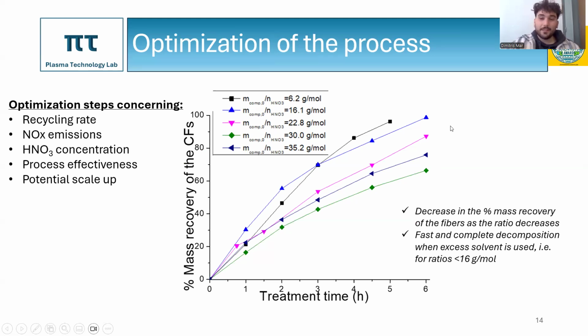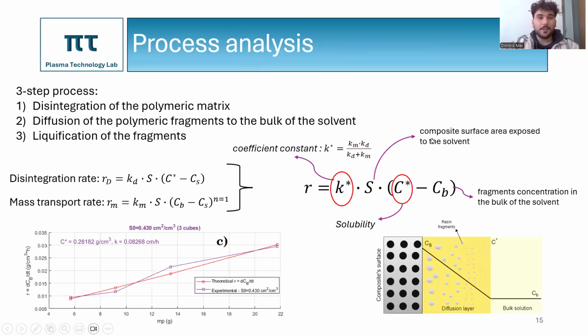Besides the optimization of the process, we try to analyze even more our process so we can fully understand the mechanism behind the solvolysis. Solvolysis is a three-step process that includes the disintegration of the polymeric matrix, the diffusion of the polymeric fragments to the bulk of the solvent, and the liquefaction of the fragments. And solvolysis can be explained by using two equations, the disintegration rate and the mass transport rate. Now in steady state, those rates are equal, and this is how we can extract a general equation right here, which can express the whole solvolysis process.